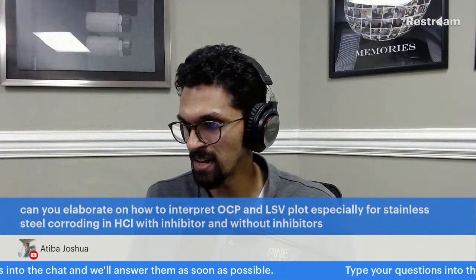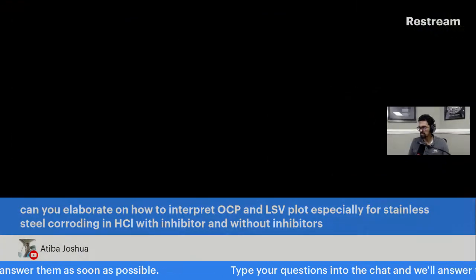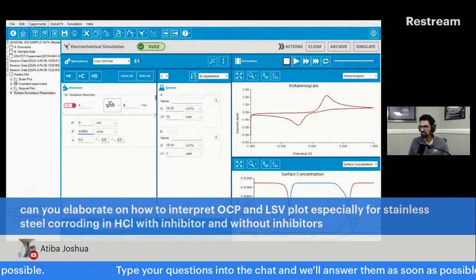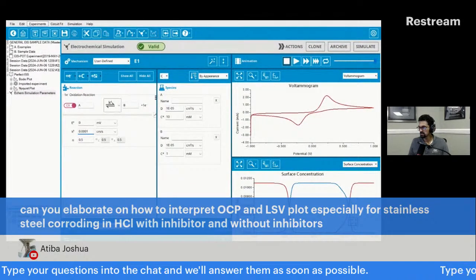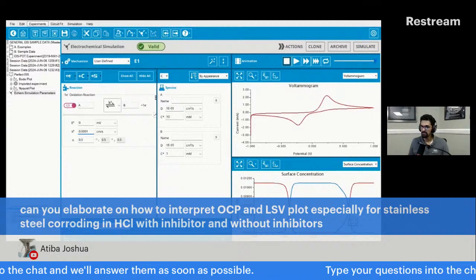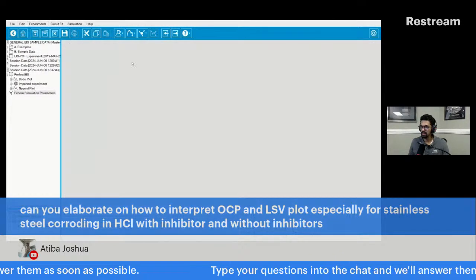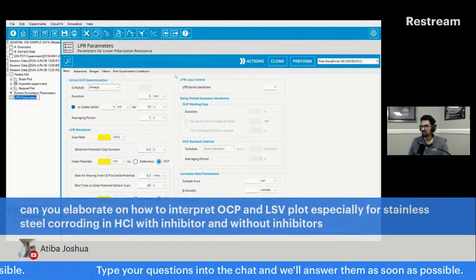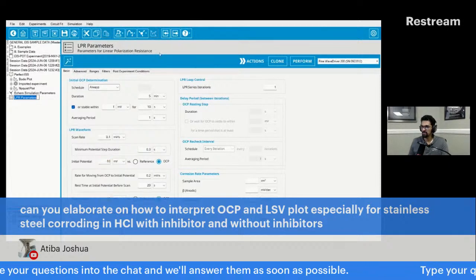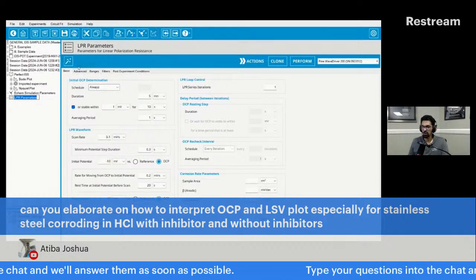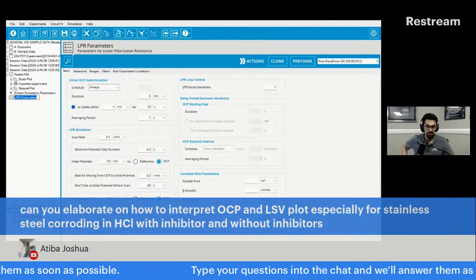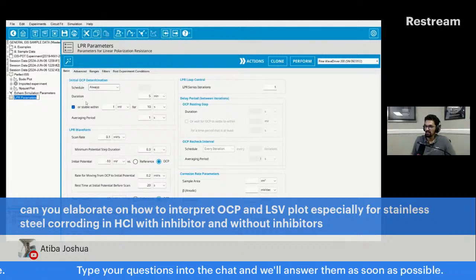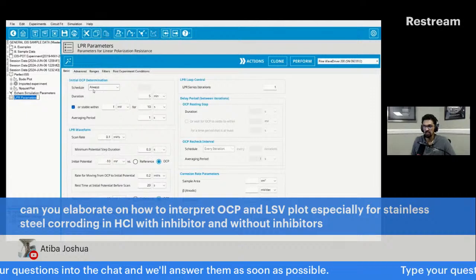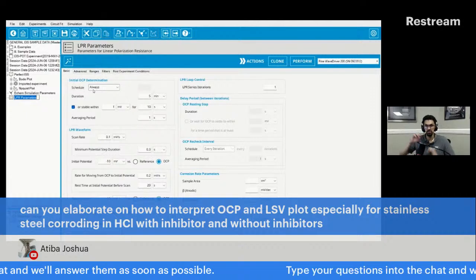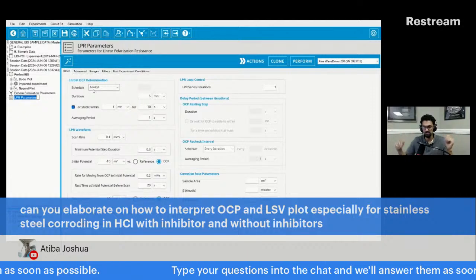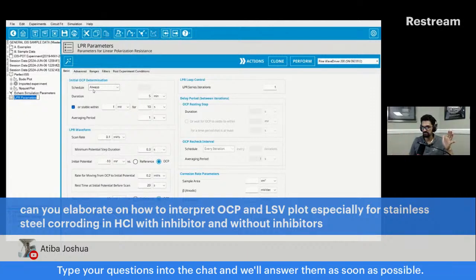Actually, let me see if I have, I can show you what the technique kind of looks like in general. So if you go to experiments, and let me just make sure that my screen is showing this. We have corrosion methods, and then we have LPR, linear polarization resistance. I'm just putting in some of the autofill automated parameters that people mostly use. And you need to determine the OCP. The OCP just kind of helps you figure out, with the other electrodes in your cell, your reference electrode, what the open circuit potential is.